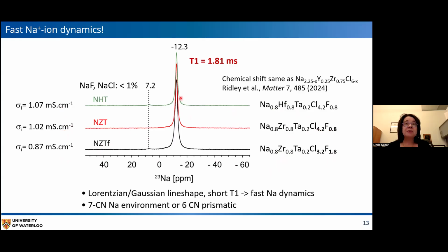But they all show a single feature in their sodium-23 MAS spectrum, and that happens to be the same chemical shift as reported for Na2.25-xY0.25Zr0.75Cl6-x by Ridley et al. in Matter. But what's more important is not the fact that it's a chemical shift. What's important is this T1 relaxation time, which is really quite short. And so that is indicative of fast sodium dynamics. And that got us quite excited when we saw this. We think the environment of the sodium is either 7 or 6 coordinate, but it's hard to tell at this point.